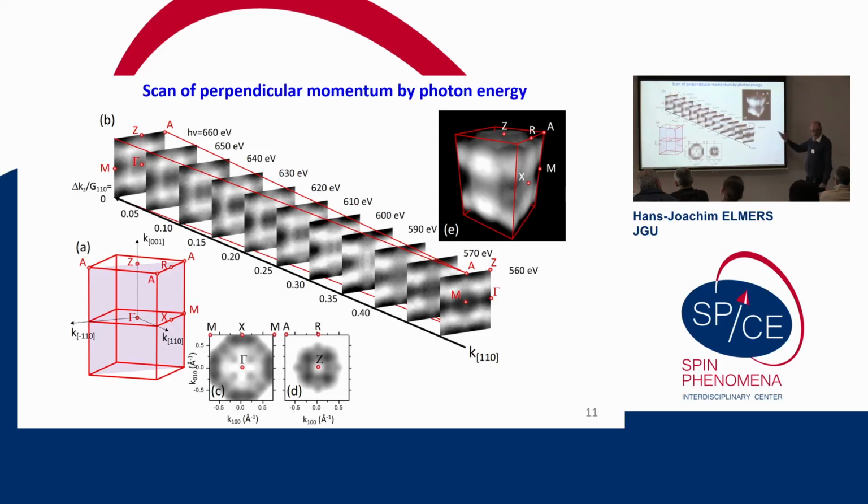By concatenating this data, we get a three-dimensional intensity array. And in principle, we simultaneously measure all binding energy. So we have a four-dimensional data array where we can take sections as we want. For example, we can plot the Fermi surface here of ruthenium dioxide. And we can now also take cuts in other planes if we want.